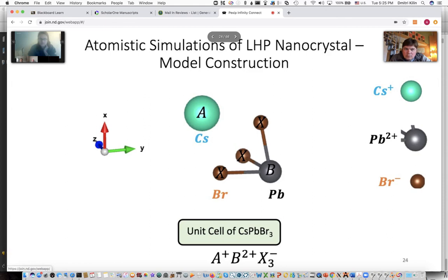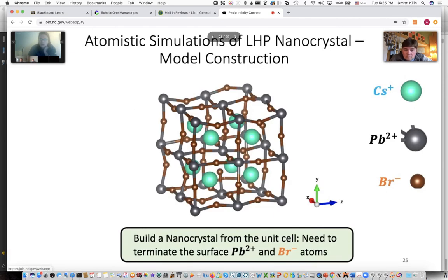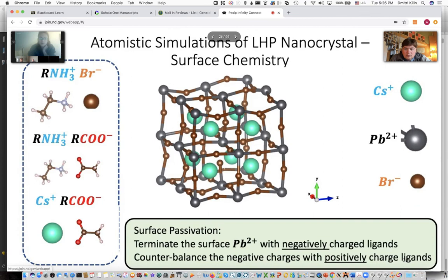And then to make our quantum dots, we repeated the unit cell 3 times in the X, Y, and Z direction. So that's the next slide. So if we replicate the unit cell 3 times, this is more or less what we're left with, a lead halide perovskite cluster. But then to make these stable or to reflect their surface chemistry in experiments, we have to choose how to passivate these surfaces. Because if we just left it like this, it would run into another cluster and just want to coalesce.